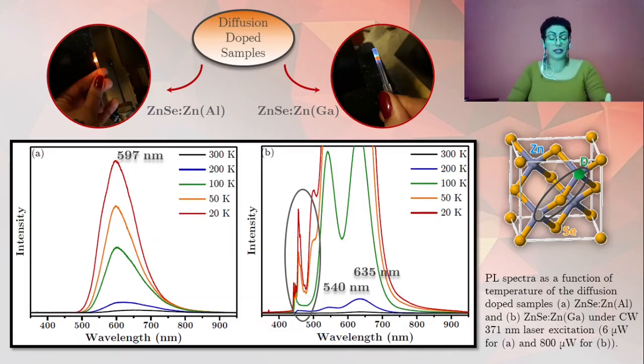Comparing the luminescence of the diffusion-doped samples with the mother sample ZnSe, we can observe that the excitonic peaks of the mother sample are also present in the gallium-doped sample, in addition to new peaks, but suppressed in the aluminum-doped sample. This result indicates that the diffusion doping method was more effective for the aluminum-doped sample, in agreement with the fact that the sample showed a more intense luminescence than the gallium-doped sample.